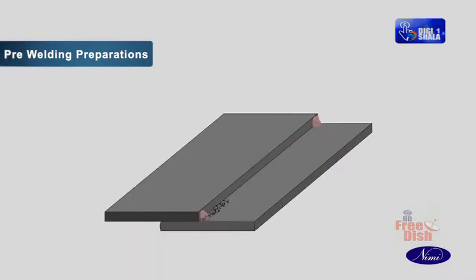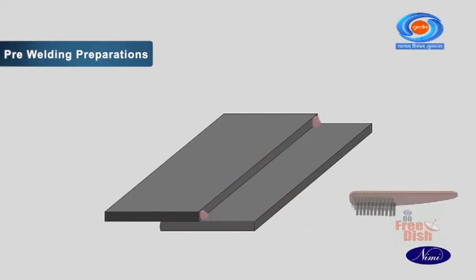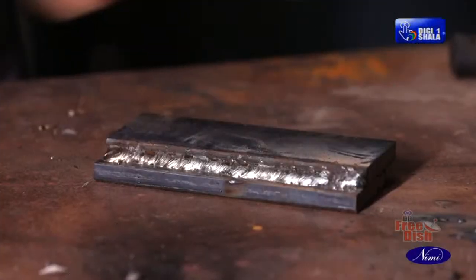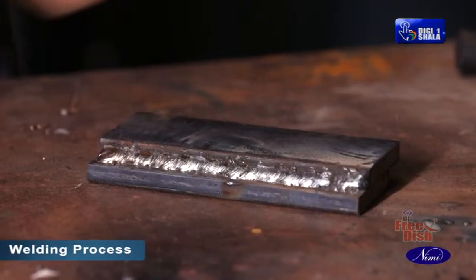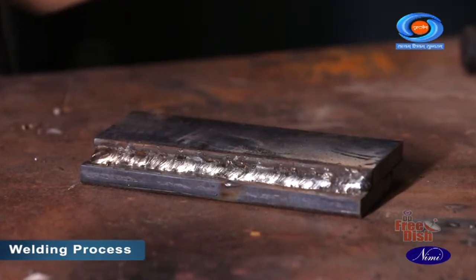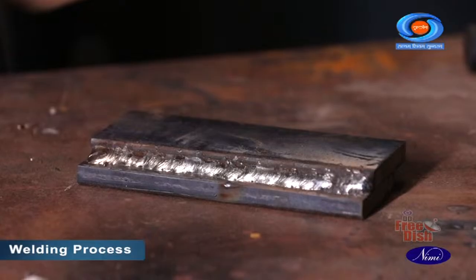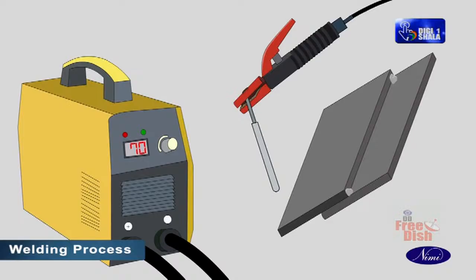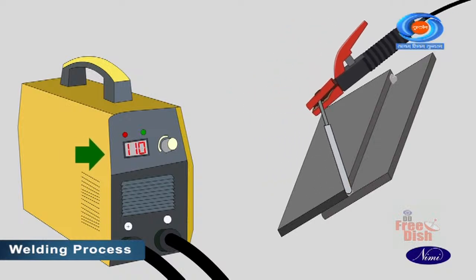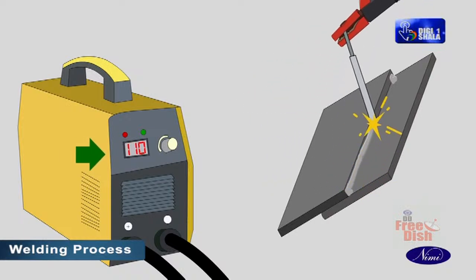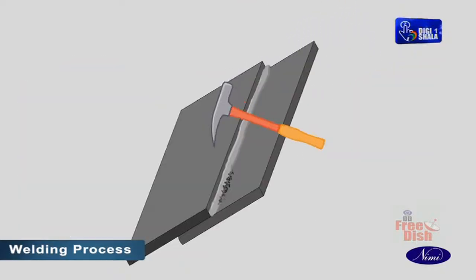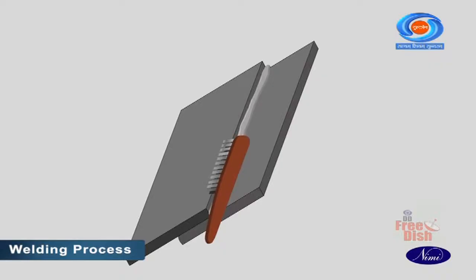Set the lap joint in a flat position and remove the slag with a chipping hammer and clean the weld with a steel wire brush. Now, let us look at how to perform a fillet lap weld on a MS plate in a flat position by SMAW process. Deposit root run by using a 2.5 mm dia medium coated MS electrode with 100 to 110 amps current. De-slag and clean the root slag thoroughly.